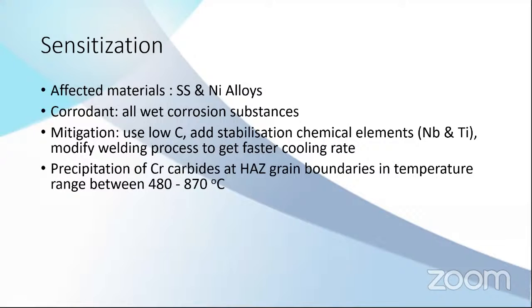So this is the mechanism. The precipitation of chromium with the carbon creates chromium carbides in the heat affected zone's grain boundaries, and it happens at a temperature between 500 to 900 in general. It normally happens during the cooling of the welding process.